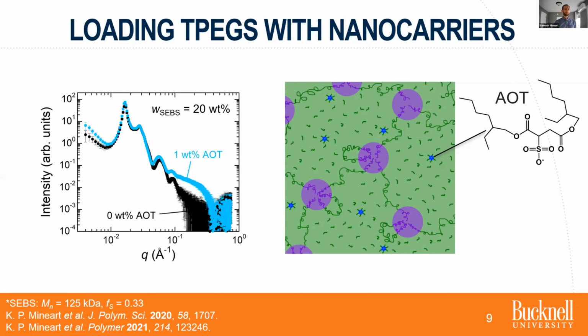And we can combine that either with oil, our aliphatic mineral oil, in the absence of AOT, which is the black curve here, or containing 1 weight percent AOT, which is the blue curve. And the basic thing you'll see here is that a lot of the features are very similar, especially at lower Q, so left half of the graph here. But as we get to higher Q, all the features kind of lift up, and especially at 10 to the -1 inverse angstroms forward, we see a raised plateau compared to the case with no AOT. And it turns out that this specific plateau indicates the presence of reverse micelles.